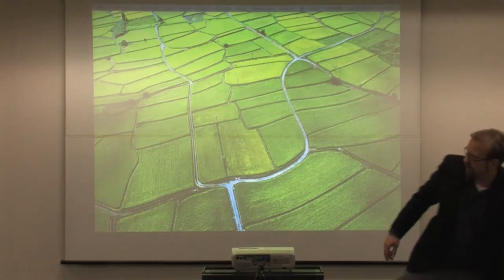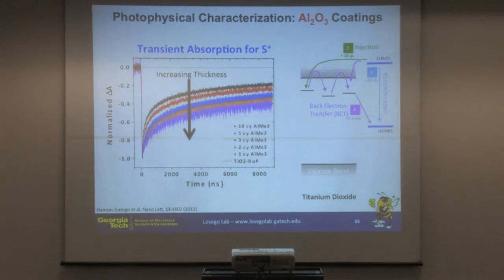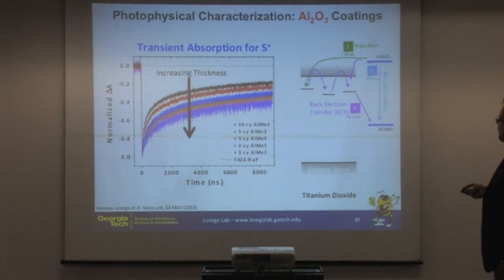We have a number of measurements that we've done. Like I said, transient absorption measurements. So in terms of looking at electron transfer rates, this is the simplest example, for alumina. These are the transient absorption spectra for increasing alumina thickness, and we're essentially tracking back electron transfer. If this state's retained, it means the electron has not transmitted back, so a higher signal here, higher in this direction from zero, indicates slower back electron transfer, right? This is a slower decay than this is. So without any ALD, we see a fast decay, fast back electron transfer. Here, slow back electron transfer.